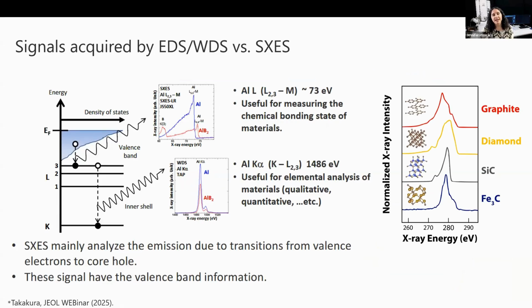So how do we actually analyze the chemical state with SXES? This has to do with how the signals differ between this technique and with EDS or WDS. So consider looking at an energy band diagram shown here on the left. For EDS or WDS, we're looking at the transition of characteristic X-rays emitted from electrons moving from, say, the L to the K shell. The shape of that peak will be less affected by the chemical state, but the spectral intensity will change in proportion to the concentration. So that allows for elemental analysis and quantification.